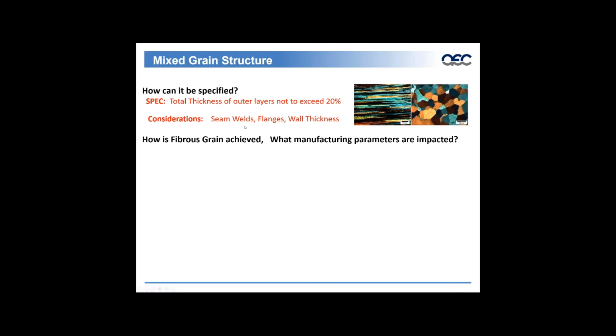But considerations that have to be taken into effect is the seam weld location. So in a porthole extrusion application where seam welds exist, typically these specifications don't apply in those areas. They typically don't apply in flanges, and wall thickness needs to be taken into consideration when those specs are applied.